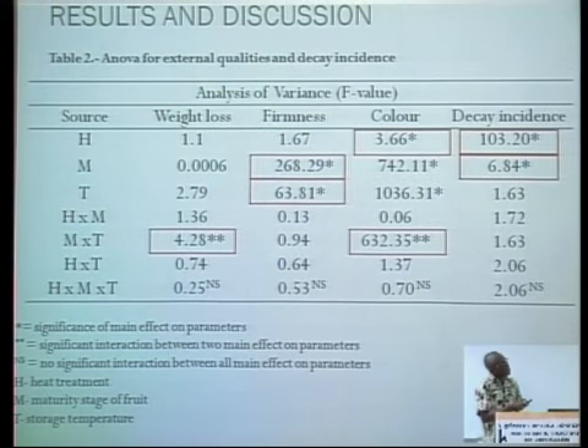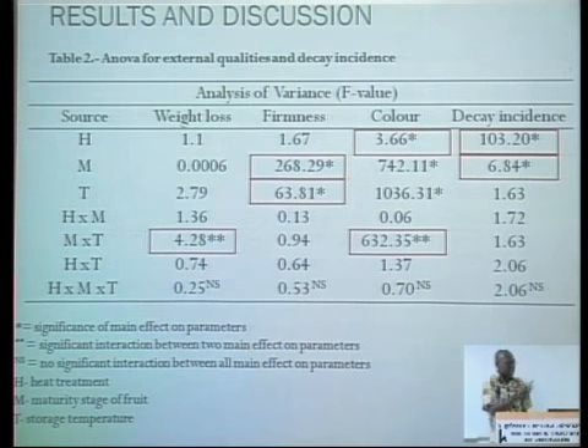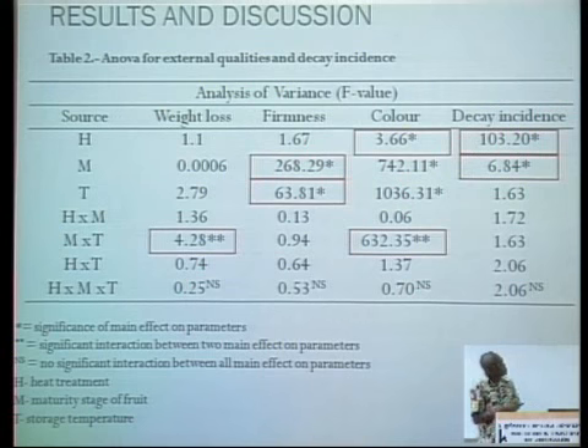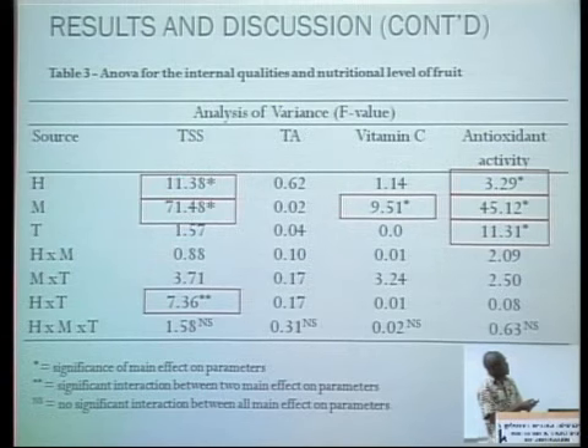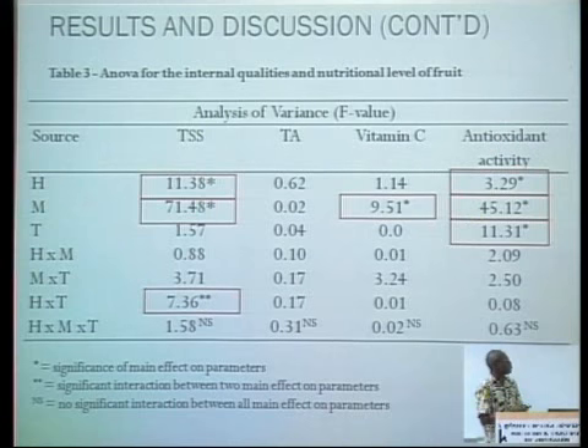And when we come to the color, these three main effects had a significant effect on the color, and we saw some interaction, as I showed in the graphs, that between the maturity stage and the temperature there was a significant interaction. And for the decay, we also saw a significant effect of the heat treatment on decay, and we also saw a significant effect of the maturity stage on the decay. And if we look at the TSS, the heat treatment had an effect. The maturity stage also had a significant effect, and we also had a significant interaction between the heat treatment and the storage temperature.